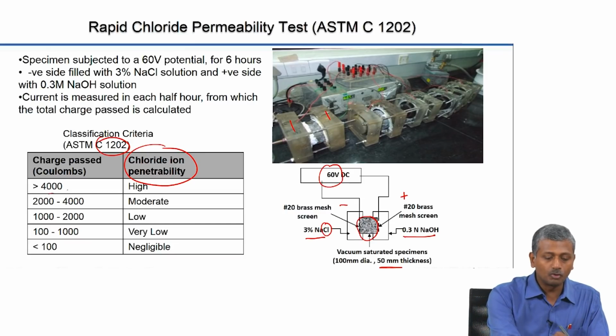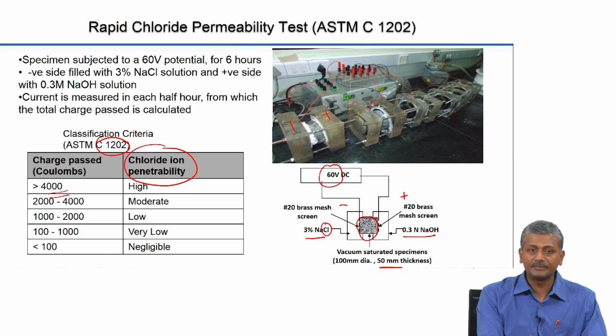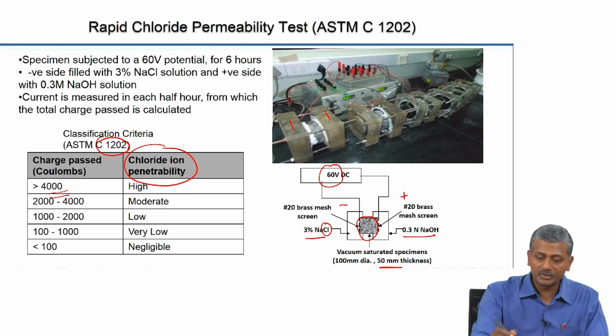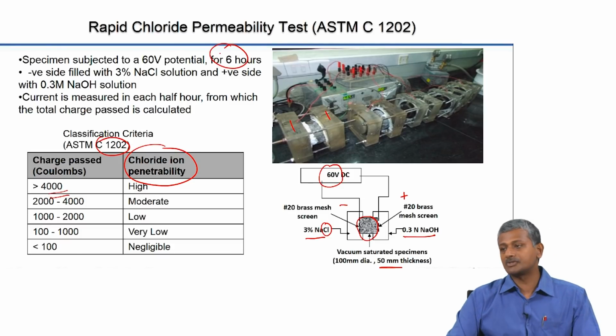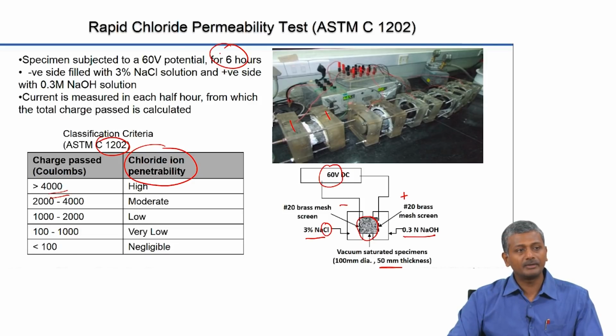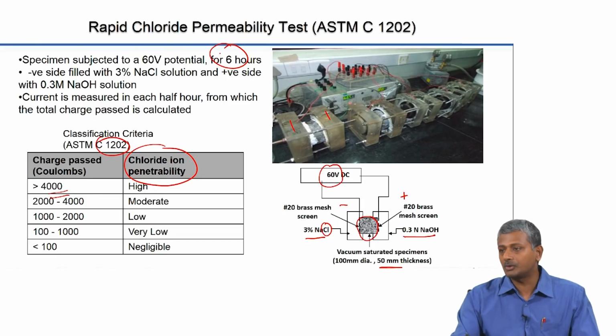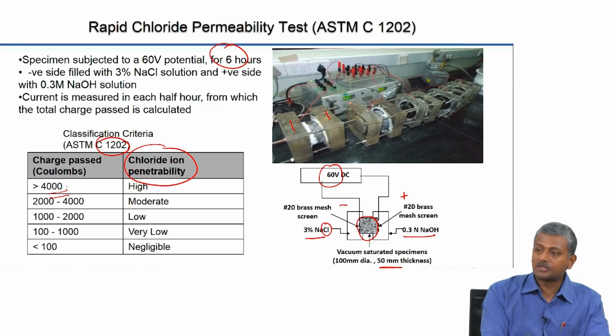And if you get more than 4000 coulombs of charge passing through the system in a total of 6 hours, so this potential is applied for 6 hours through your specimen, and then you determine the extent of current passing through from time to time and convert that to the charge, because you know that charge is equal to current multiplied by time, right, coulombs equal to ampere into second. So you convert that to a charge passed in terms of coulombs.